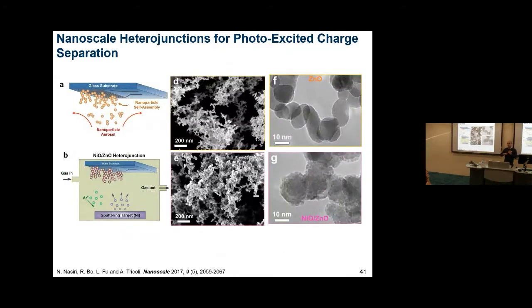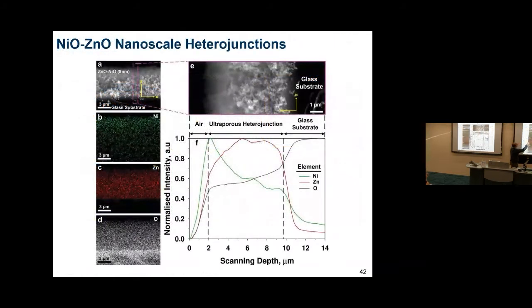There are some issues - the absorption and desorption of oxygen is slow, so we thought about creating a nanoscale heterojunction. We deposited nickel on this porous film, for example by sputtering, and created this structure. If you look into the cross-section, you can see that nickel is not uniformly distributed, but it reaches till the end of the film.